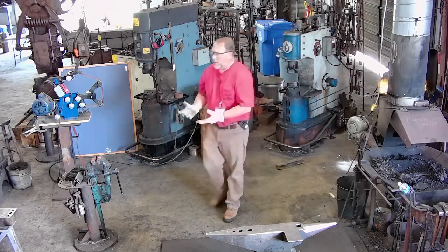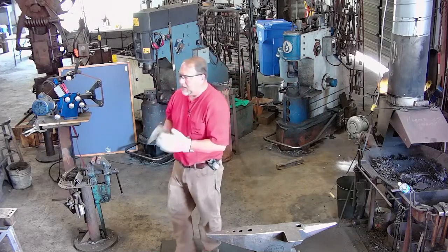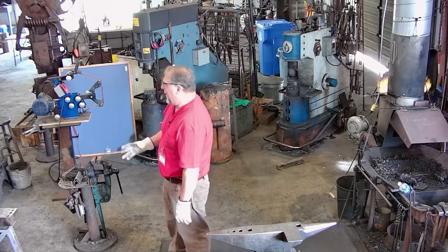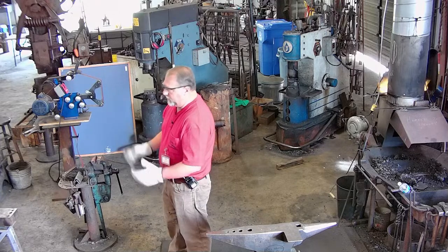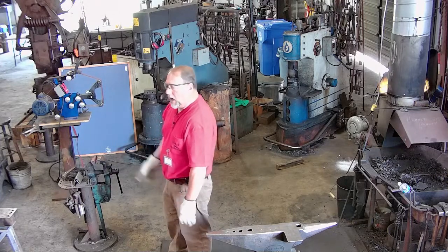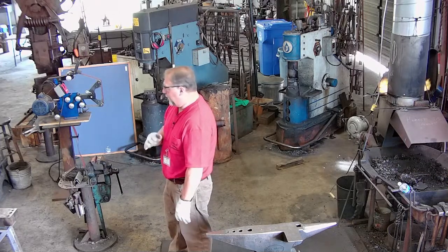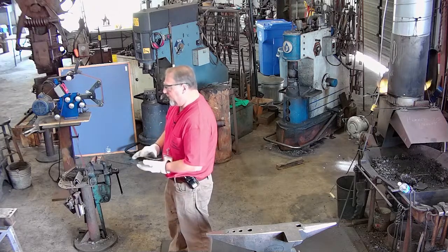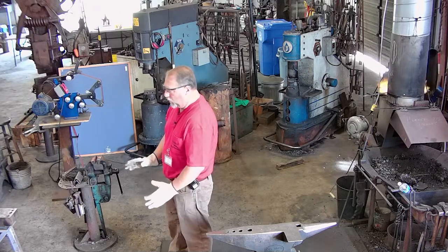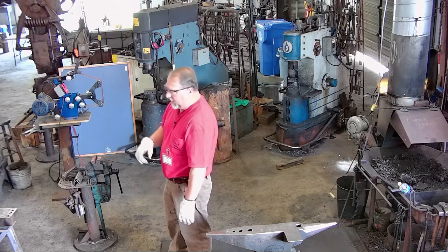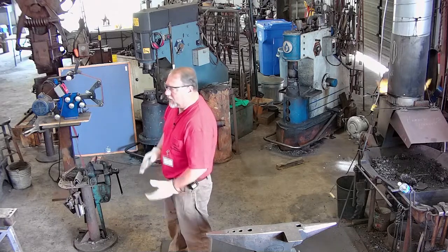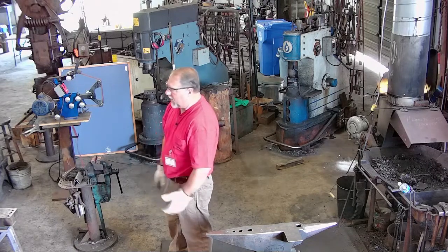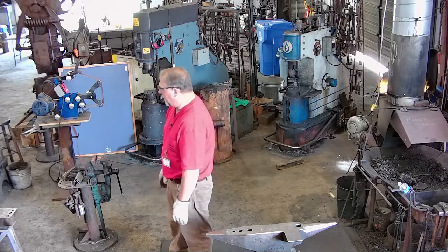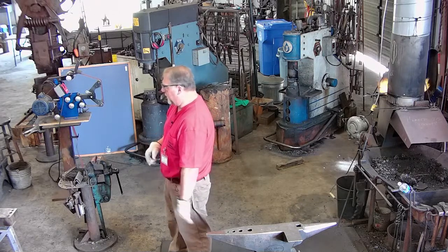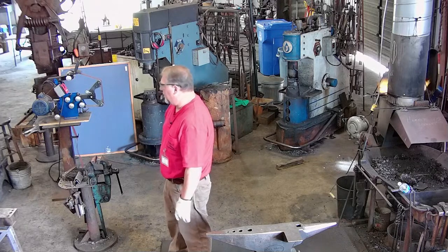On my initial weld sets, I make sure that I'm barely tapping that billet. If you smack it too hard, you'll blow those layers apart and you'll ruin your billet. So I'll run two or three iterations of just barely tapping that billet, reducing the thickness of it, and getting a good forge weld. Then I'll rotate it on its side, put it in a vise with a grinder, and grind off all those welds that are in that billet, so I don't get that mild steel from the MIG mixed in with my billet.